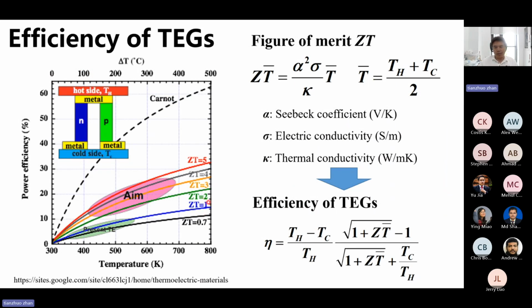But thermoelectric materials also have limitations. The biggest one is that the efficiency of TEGs is very low. The efficiency of a TEG can be calculated using the dimensionless parameter ZT of the thermoelectric materials. The present thermoelectric materials have a ZT of around 1, so the power efficiency of the TEG is lower than 10%. The aim is a ZT value of around 3 or 4. If we can increase the ZT value to 3 or 4, we can improve the efficiency of TEGs to more than 20%.